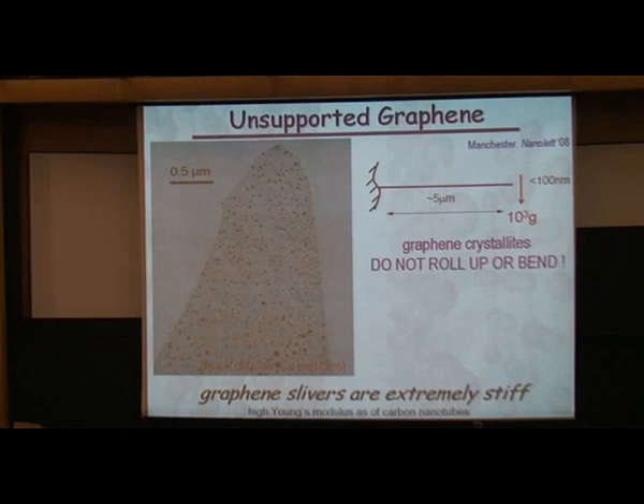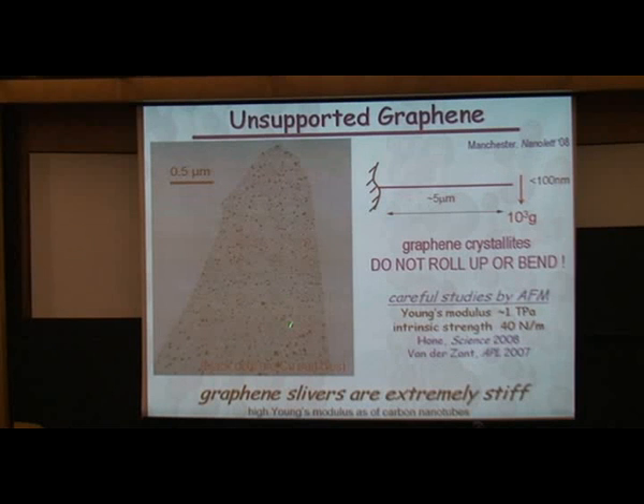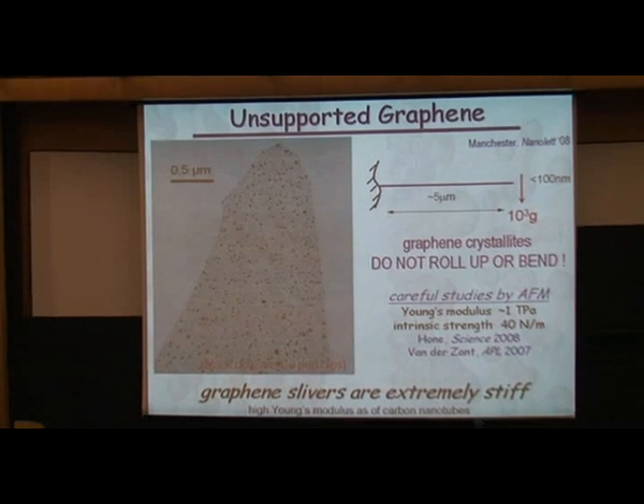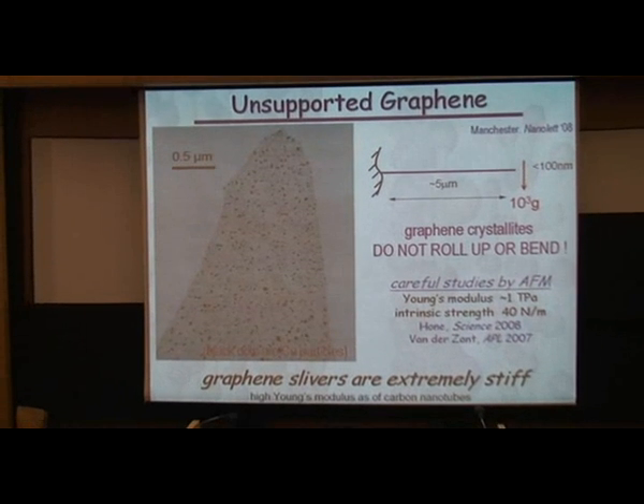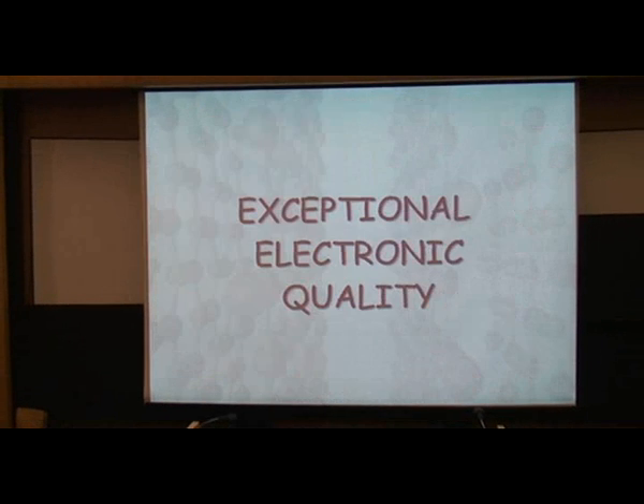That's an observation which continues shocking me, because usually, according to thermodynamics, it should roll into a scroll, and it doesn't roll into a scroll. There are huge barriers we don't understand. We only know that stiffness helps. You can do it with AFM more carefully, but this is a qualitative observation: the stiffness and strength of the material is really shocking. Not much is known yet about mechanical and thermodynamic properties of graphene as a freestanding object.